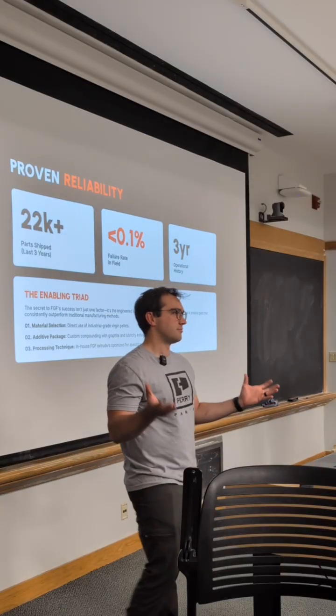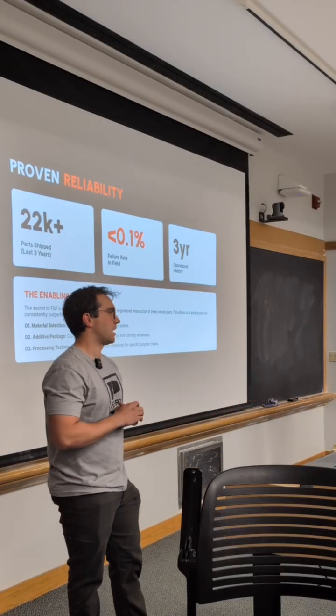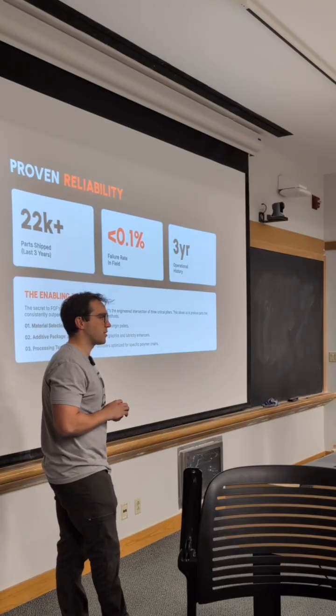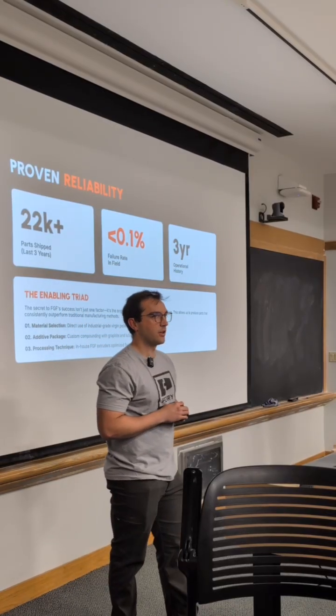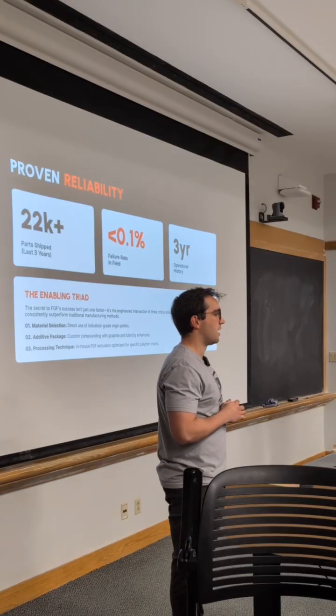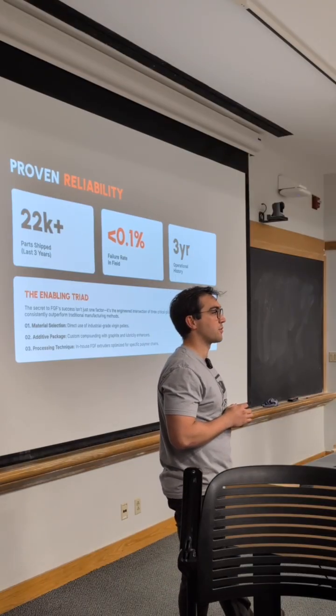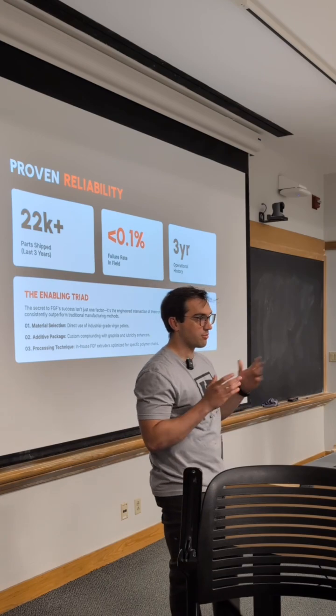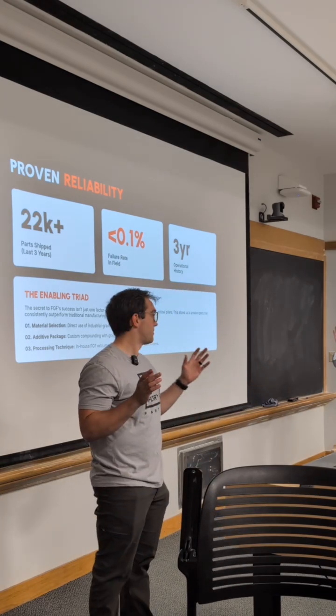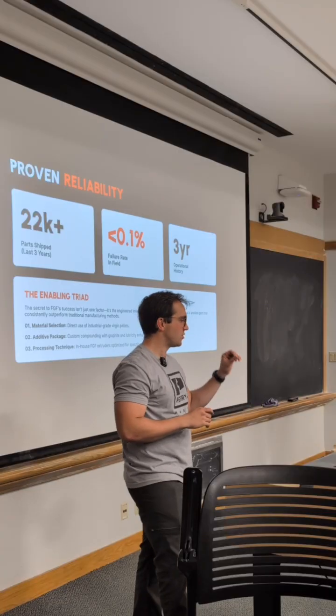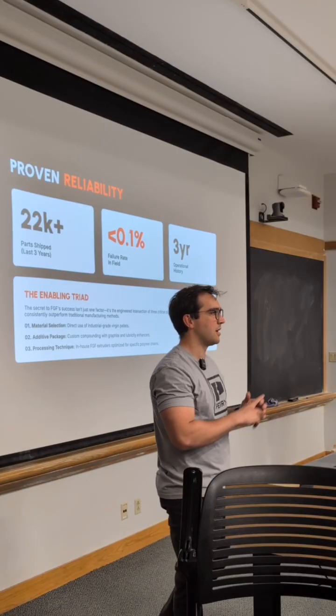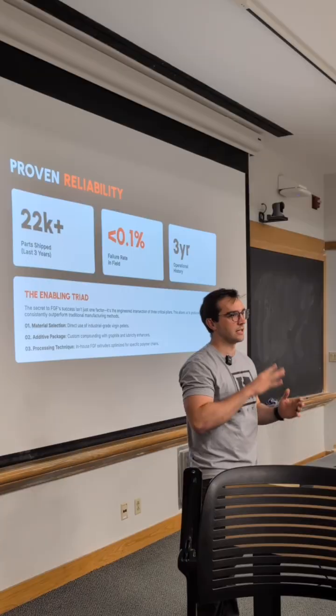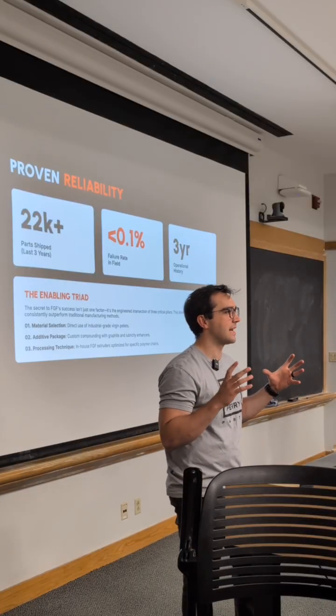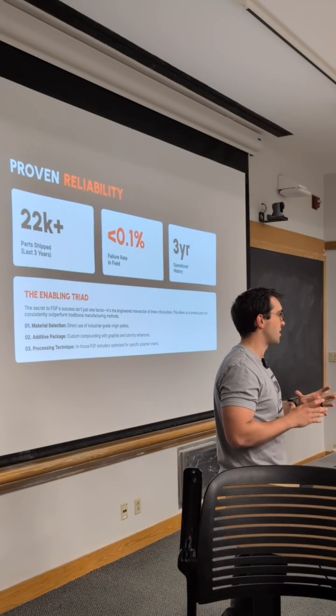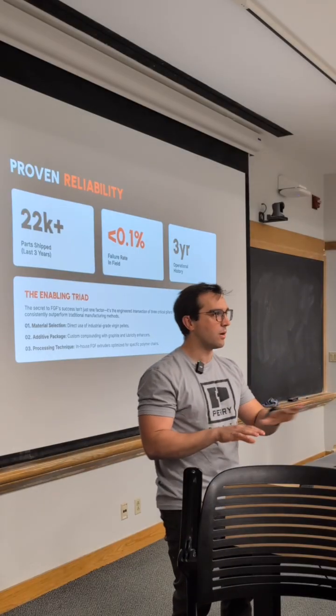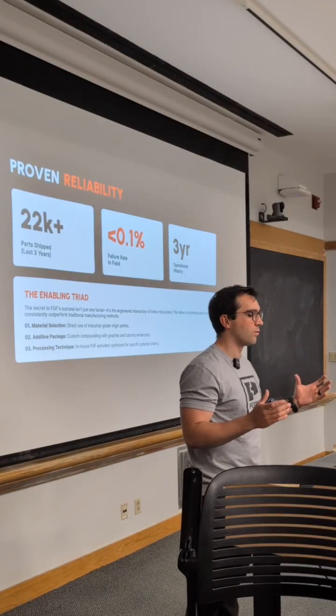So, we're making 3D printed suspension parts. What does reliability look like? We've been selling these for about 3 years. We've shipped 22,000 parts to date. We have a failure rate of less than 0.1%. With filament, that failure rate was closer to 30%. So pretty dramatic change. That's due to pellet extrusion, material selection, material compounding, material handling. You put all that together into a cohesive manufacturing story, and that's how you get there. It's not any one individual part, it's the system as a whole.